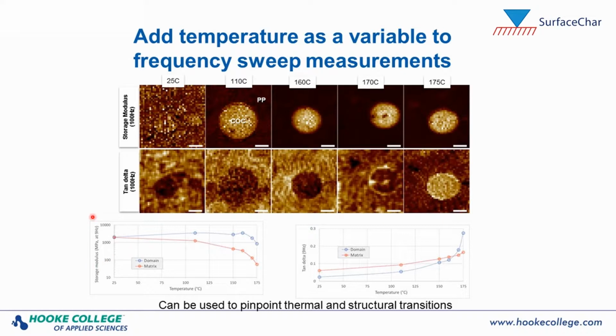And then we can quantify what the moduli are on the polypropylene and the domain of the COC, and we can plot that as a function of temperature from our data, both for the storage modulus and for the loss tangent. And we can see that the storage modulus as a function of temperature for these two components diverges because polypropylene very quickly approaches its thermal transition point. In the loss tangent, what we see is a crossover in the relative loss tangents between the two materials.